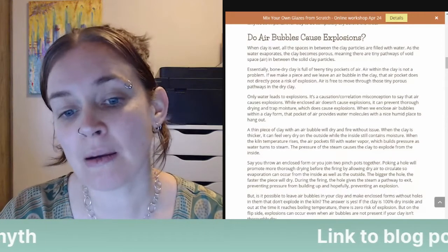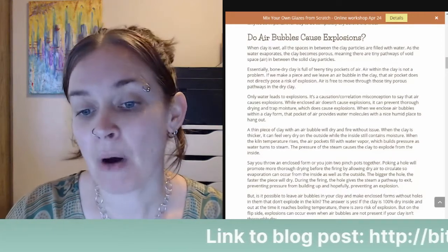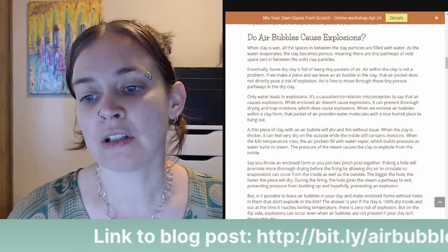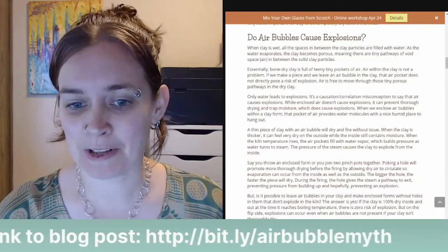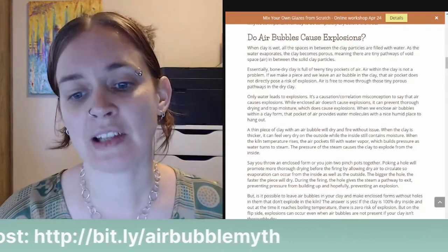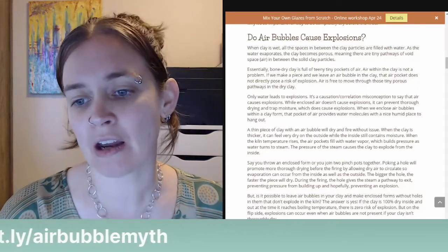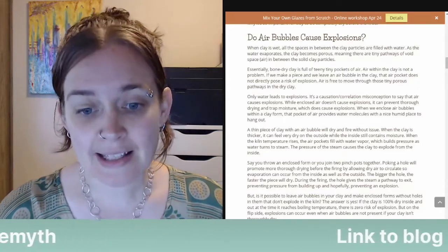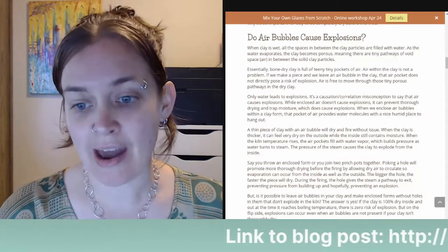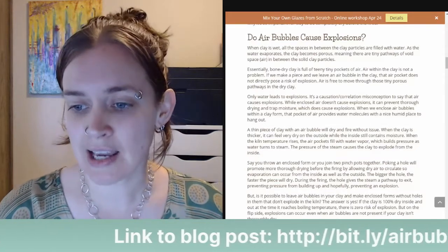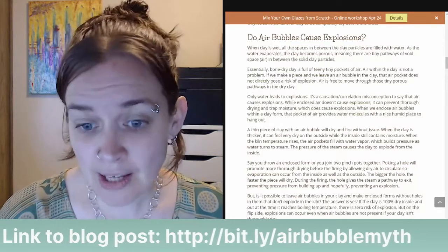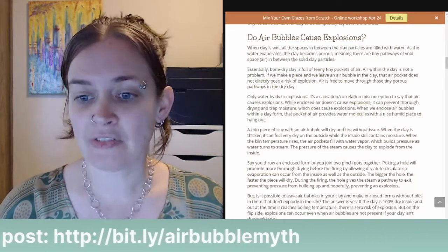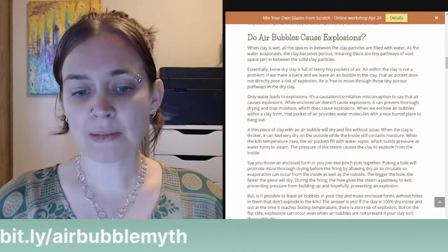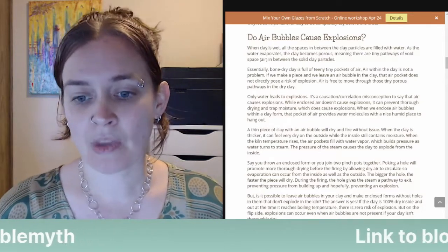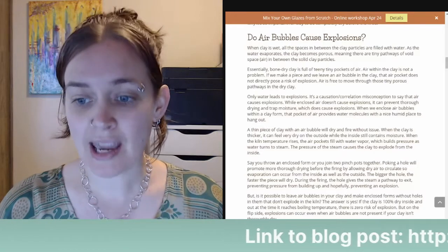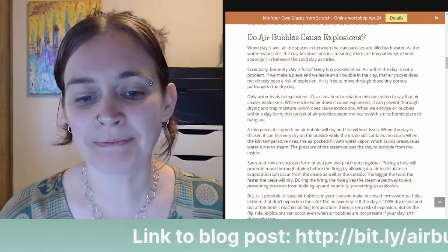When we enclose air bubbles within a clay form, that pocket of air provides water molecules with a nice humid place to hang out. A thin piece of clay with an air bubble will dry without issue. When the clay is thicker, it can feel very dry on the outside, while the inside still contains moisture. When the kiln temperature rises, the air pockets fill with water vapor, which builds pressure as water turns to steam. The pressure of the steam causes the clay to explode from the inside.